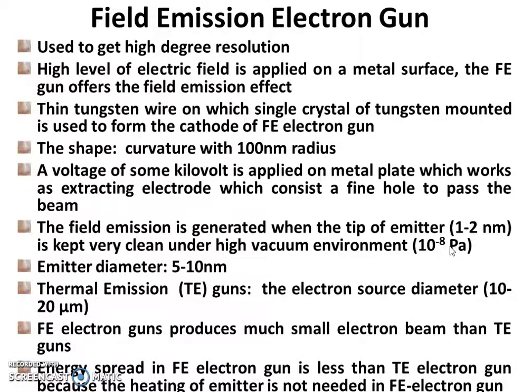The field emission is generated when the tip of the emitter, which is 1 to 2 nanometer in size, is kept very clean under a high vacuum environment, and the vacuum remains nearly 10 to the power minus 8 Pascal. And the emitter diameter varies from 5 to 10 nanometer. In thermal emission electron guns, which are called TE guns, the electron source diameter remains 10 to 20 micron. So this is the basic difference between FE guns and TE guns.